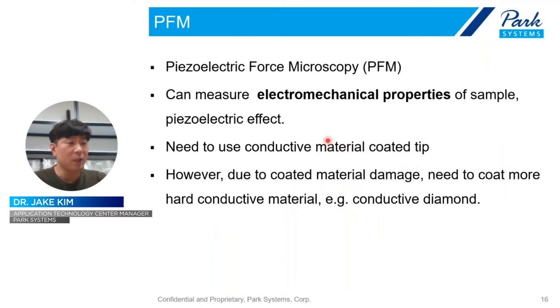Next is the PFM, the piezoelectric force microscope. Using PFM, we can measure the electromechanical properties, simply speaking, the piezoelectric effect. And of course it is an electrical property measurement, so we need to use a conductive material coated tip. But actually EFM and KPFM are non-contact mode based, while PFM is contact mode based, so we should apply a harder conductive material like a conductive diamond.